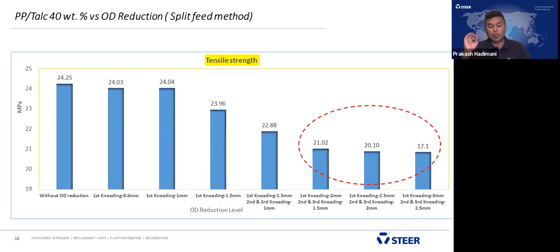polypropylene or any polymer, it has to melt 100% and form a homogeneous dispersion, so that when you feed the talc from the first side feeder, it has to wet and disperse completely. If there is no wear and tear, then it maintains the mechanical property. That is the sign we are getting.